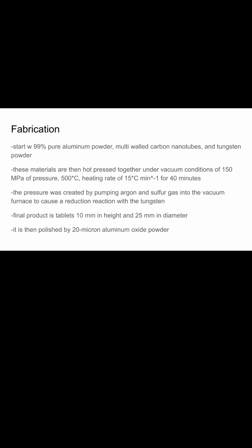Fabrication begins with 99% aluminum powder, multi-walled carbon nanotubes, and tungsten powder. These materials are then hot pressed together under vacuum conditions of 150 megapascals of pressure, 500 degrees Celsius, a heating rate of 15 degrees Celsius per minute, for 40 minutes.